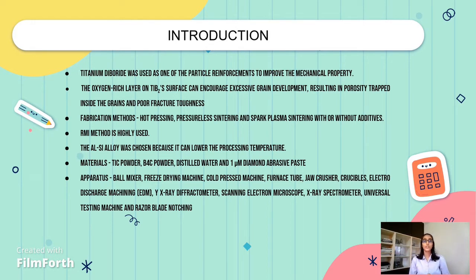Furthermore, the oxygen-rich layer on the titanium diboride surface can encourage excessive grain development, resulting in porosity trapped inside the grain and poor fracture toughness. Hot pressing, pressureless sintering, and spark plasma sintering with or without additives are the currently available manufacturing processes for silicon carbide titanium diboride ceramic composite. The following techniques, on the other hand, have high cost and high processing temperature as their common characteristics.